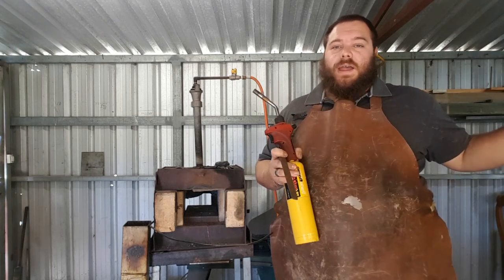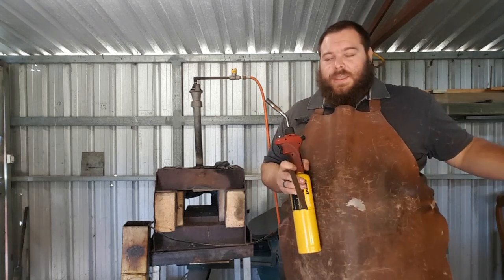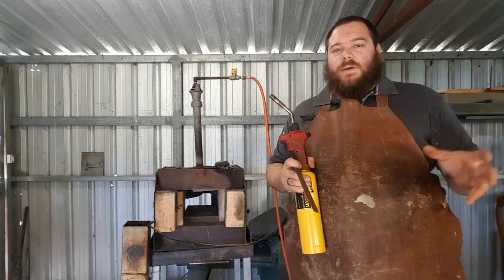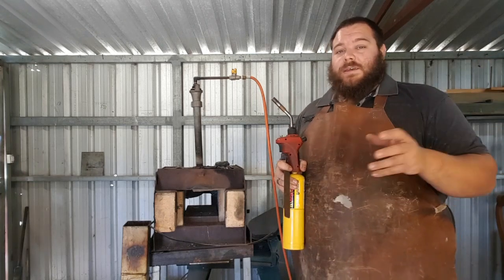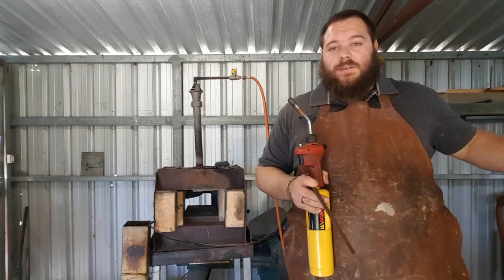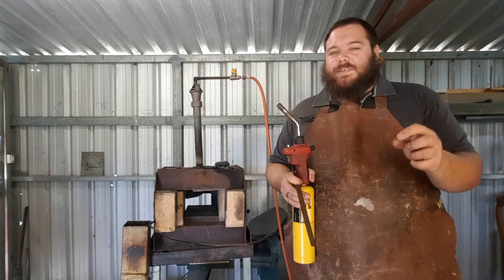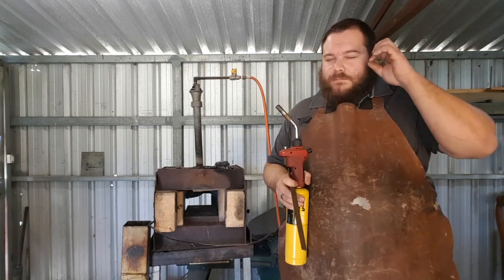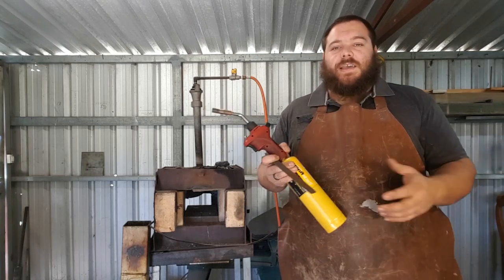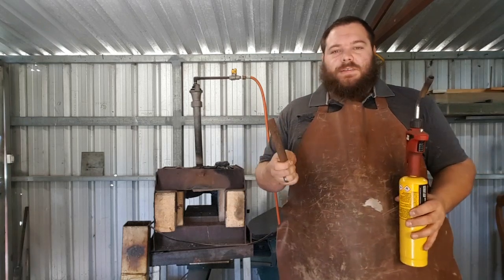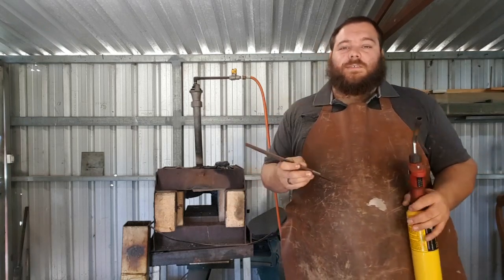And so you'll chip your edge no matter how well you temper it. Whereas if you made the same thing using beach sand and Play-Doh, or beach sand and some other kind of thing, you may still get a loss of grains, but the grains will be much smaller, and that's the case with steel. So that's an important thing to keep in mind, is that you want to relax the grain structure.